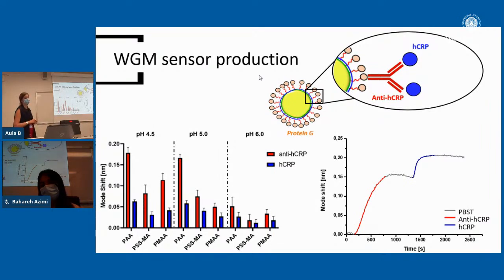In this case, the blue bond. So as you can see on the right, we could detect the binding of the antibody to our sensor in red, and then we could detect the binding of the antigen to the antibody in blue. And when we analyze this interaction at different pHs and in the different polymers, we observed that polyacrylic acid in all the conditions gave out the best results. So from this data, our protein G microsensors were produced on polyacrylic acid layer-by-layer coated particles.